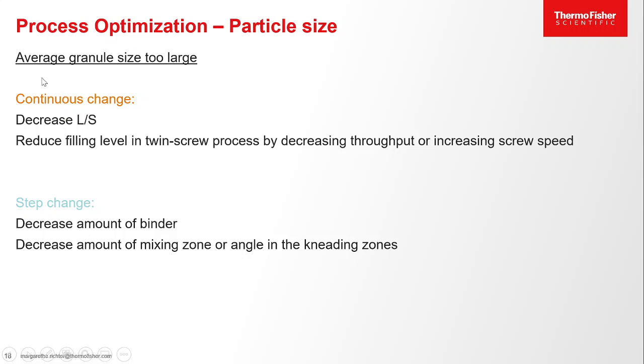So let's say your average granule size is too large. What can I do on a continuous level? Well, that's the simplest thing. Too large granules, well, decrease the liquid to solid ratio, and then you'll have smaller particles. But you can also reduce the filling level in the twin-screw by decreasing the throughput or increasing the screw speed, and this will also lead to smaller particles on average. Then a step change could be to decrease the amount of binder, so change the formulation slightly. And you can also change the screw configuration by decreasing the amount of kneading elements in the zone or decreasing the angle.